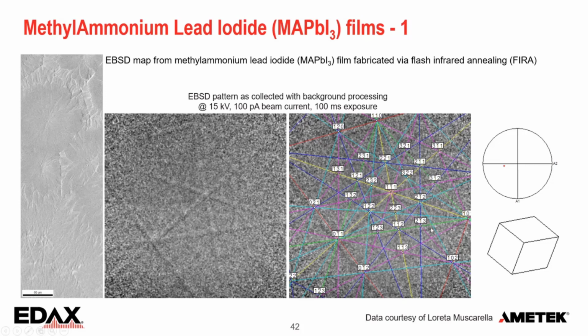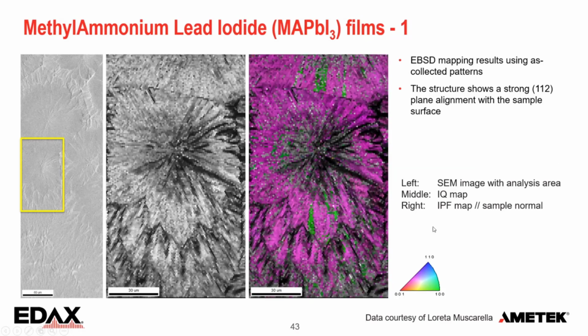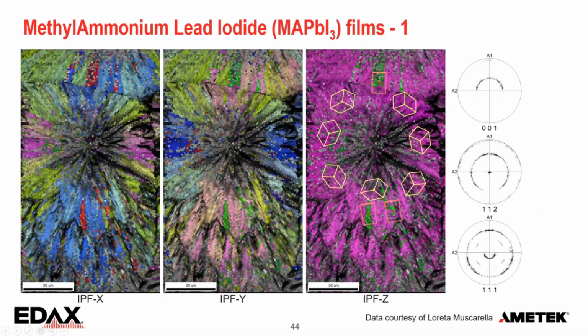We get patterns, we can index those, and we get a beautiful EBSD map. So now we can get full area. This is not very topographic, so we get very consistent indexing. Two orientations effectively are sticking out. There's this purplish, pinkish color, which is the 112 orientation. And we have these green bands, which is the 100 pointing at us.